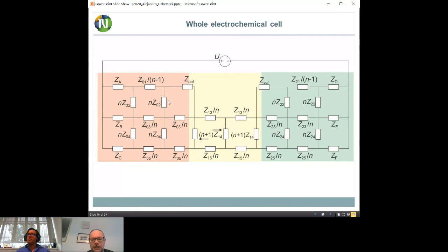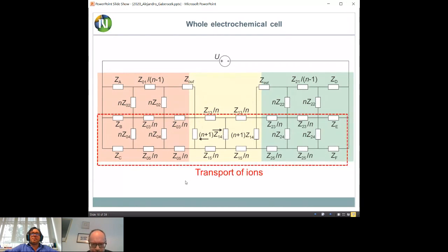Although we usually say, okay, lithium is flat electrode, I will show you clearly with pictures and everything later on that lithium, especially cyclical lithium, is porous and can be described effectively with the same general scheme as the cathode. That's a sort of beauty of this symmetry here. Even if you have anode cathode, you can have this kind of symmetrical case, and then there is electrolyte in between. Now, very generally, I will go very briefly through this.